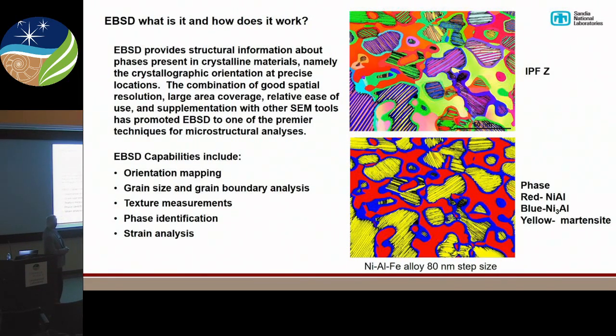The nice thing about this, I think, really makes the SEM a complete tool now. So with an SEM, when it first started, we took beautiful images of surfaces and saw fracture surfaces and all sorts of neat things. As we added EDS or chemical analysis, WDS, we now made a tool that could do both morphologies and then elemental analysis. And now with EBSD, we've really covered the gamut. We have imaging, we have analysis, chemical, elemental, and now we have the crystallography of the sample as well. So it makes the SEM a complete tool for materials characterization. And in some cases, I think it pushes the TEM to sort of the background for what we want to do.